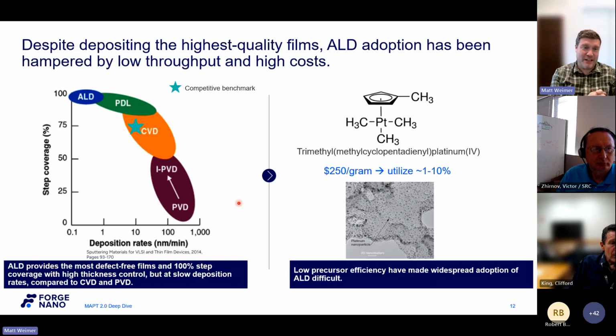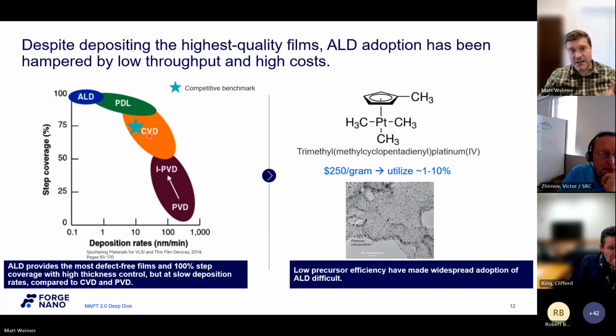So I love ALD. I've been talking about how great it is, but the main drawback is it's slow. You get great step coverage, but the deposition rates, even for the fastest processes, TMA water, the typical ALD process, you can get to maybe 10 nanometers a minute, but really that's in a very specific situation. So normally it's considered to be very slow. We've been told that once you get to this 10 nanometer per minute mark, things become a lot more interesting. So that's the first thing.